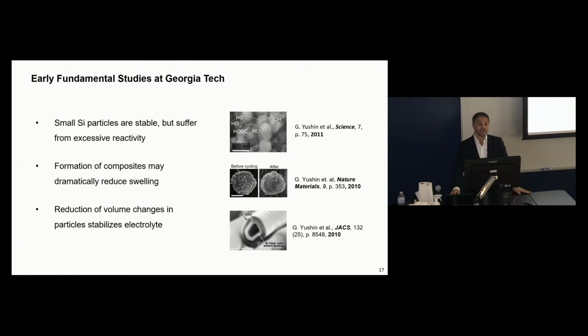And so when I joined Georgia Tech over a decade ago, I started to look into fundamentals of silicon chemistry. And together with other colleagues around the globe, we realized that small particles can be made stable, right? You will have no mechanical instability in small or nanoparticles of silicon. However, small particles always have very high surface area, so all this electrolyte decomposition now happens at much higher surface area, so you have much larger degree of undesirable reactions, right? So you can have even faster degradation.